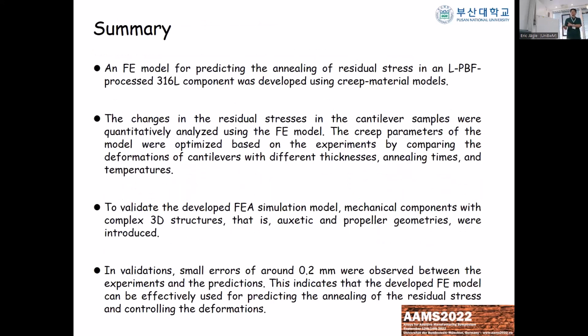So in summary, a finite element model was developed to predict the evolution of residual stress during the different annealing conditions, and the changes of the residual stress have been predicted by the creep model, which has been calibrated by the experimental data. So to validate the developed model, we produced two different complex 3D structures, and it seems that our developed model works very well. This is the end of my presentation. Thank you very much.